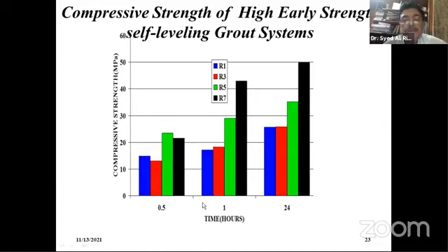So you can see that in some formulations, after 24 hours, I was able to obtain a strength of 50 megapascal. 50 megapascal, when you multiply it with 145 or 150, so that is a lot of strength. So all these green and blacks, they are the good candidates for high early strengths. But of course, in this case, I used a blend of cements. Calcium aluminate cement was used, and OPC was used. Some accelerator was used. Some retarder was also used. And I had to pack all the structure.